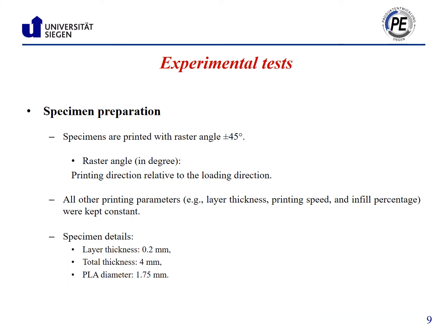In this study, the specimens were printed with plus minus 45-degree raster direction, and by definition, raster direction is the printing direction relative to the loading direction. All other printing parameters such as printing speed, layer thickness, and infill percentage were kept constant. In detail, specimens were printed with a layer thickness of 0.2 mm and a total thickness of 4 mm.